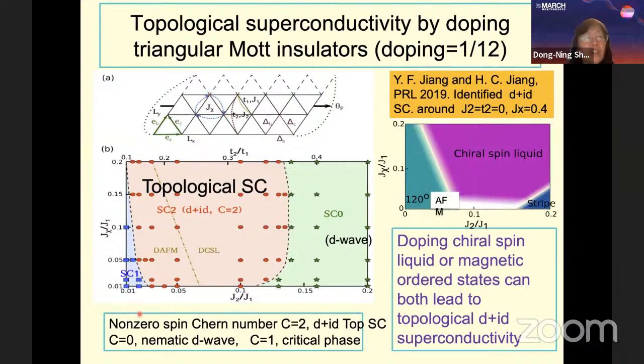We also included a chiral interaction, which involves the spin on the nearest 3 sites forming a small triangle. In that quantum phase diagram, even when we go to very small 3-spin interaction, we still have 3 different quantum phases when tuning J2 over J1 or T2 over T1. Those 3 phases are a topological superconducting phase with Chern number equal to 1, a Chern number equal to 2 topological superconducting phase, and a D-wave superconducting phase with Chern number equal to 0.